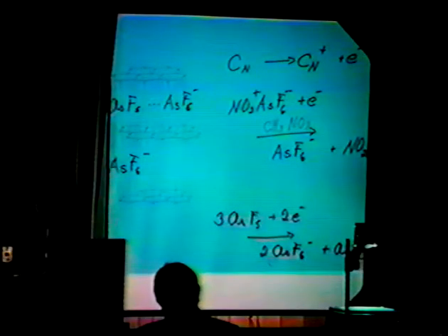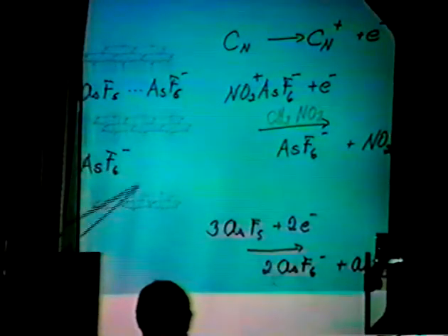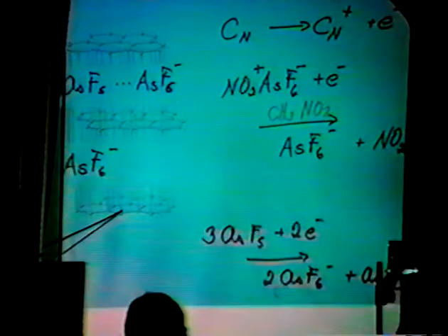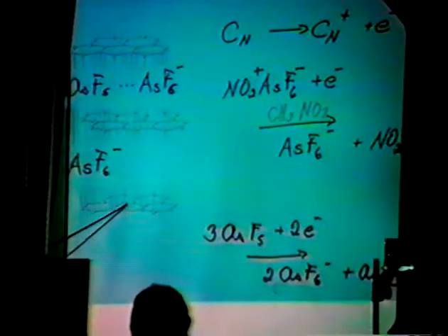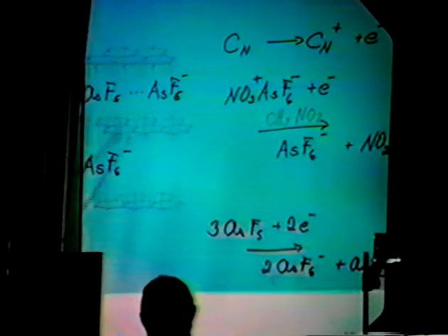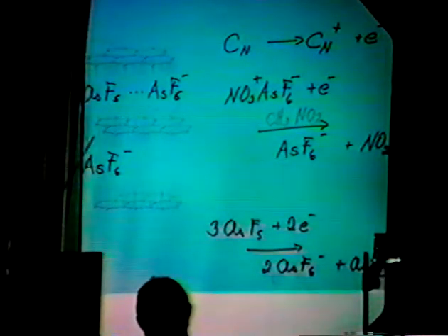Here we have the structure of the graphite, and as you can see, these layers are not stacked hexagon over hexagon. Each alternate layer is shifted. So this layer and this layer are hexagon over hexagon. This layer puts one of the carbons over the hexagon below. So we can spread these layers of graphite apart by putting intercalants in the layers of graphite.